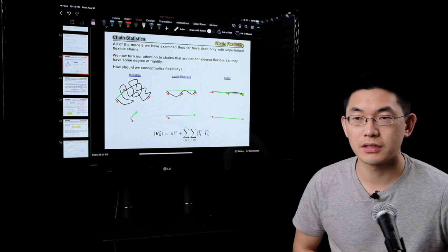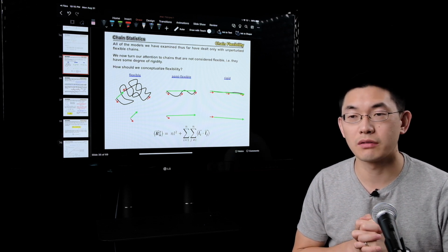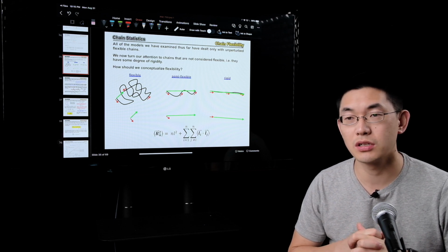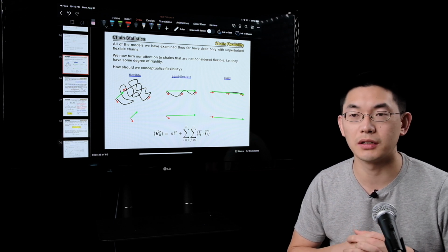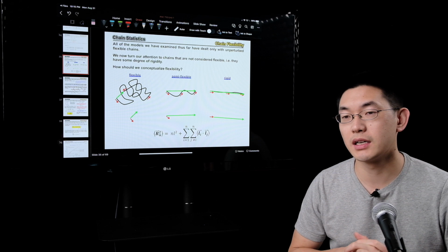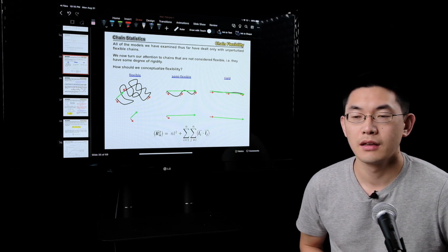As we have discussed in the previous few lectures, the expansion of the chain coil is due to the limits of the bond. So if you have, for example, the free rotation chain model compared to the free joint chain model, the expansion factor would be equal to 1 plus cosine theta divided by 1 minus cosine theta, where theta is the bond angle, okay?